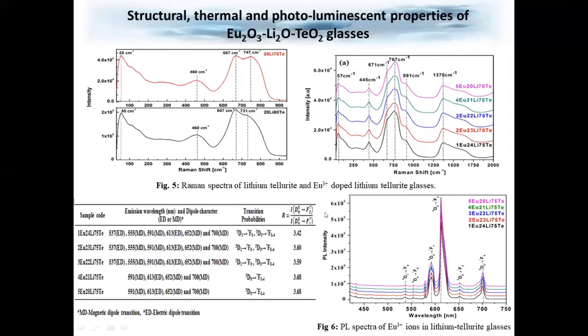And these are the PL intensity curves. We can see very strong, very intense peaks. The counts are almost 6 million counts, and there are no concentration quenching effects. When you increase the europium oxide concentration, because the glass network is expanding, the distance between the europium ions is increasing, although their concentration is also increasing. And the intensity of the photoluminescence yield increases with an increase in europium oxide concentration.